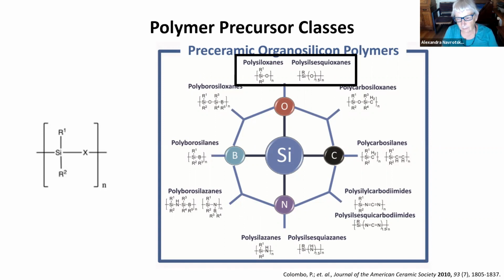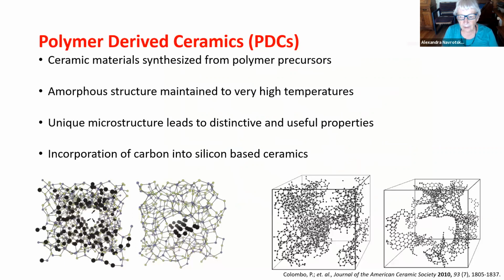So again, for example, we can use these two molecules as starting materials. So if we make polymer-derived ceramics out of them, they contain, and I thank Peter Kroll for some of these diagrams, one soon realizes that they're much more complicated in structure than something that is amorphous, random, and uninteresting. In fact, to a first approximation, they contain two hopelessly intertwined, what one sometimes calls Plummer's nightmare, fractal networks with a low fractal dimension. One network is carbon-rich and one network is silica-rich.